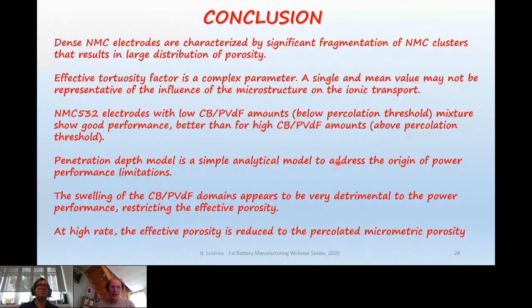transport. These NMC 532 electrodes with low CB-PVDF amounts, below the percolation threshold, show good performance, better performance than for higher CB-PVDF amounts above the percolation threshold. This penetration depth model is not from us, but we have brought some improvement in this model or its use, and we may say that it is a simple analytical model, interesting to address the origin of power performance limitations.